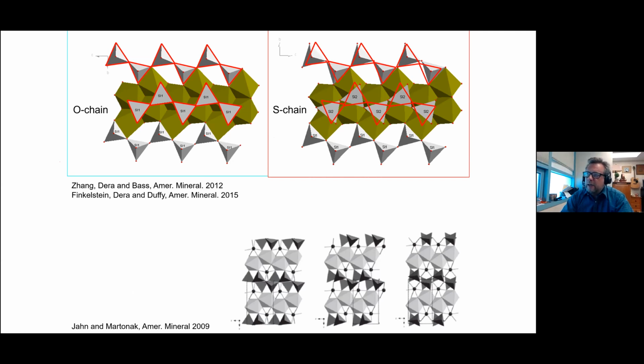So using the crystallographic software for analyzing the data, we solved the structure of the high pressure phase. We saw that there's a significant change in the kinking angle of the silicate chain, not a change in the coordination number. This phase transition was not known before. It was just a little bit above the threshold of pressure that was comfortable for the classical high pressure single crystal crystallography. So being able to conduct this experiment to slightly higher pressure, we were able to reveal these details. This was also a transition that was predicted by first principle calculations by Sandro Jahn and Roman Martonak in 2009. So we were able to reproduce that something that theory predicts really happens in reality.